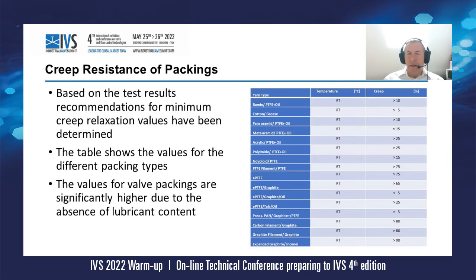The table shows the different packing types that have been tested. We start with ramie, PTFE and oil, cotton grease packings, para-aramid and meta-aramid, both with PTFE and oil impregnation, acrylic, PTFE and oil, polyamide, PTFE and oil, Novoloid, PTFE impregnated, PTFE filament packing with a PTFE impregnated dispersion, ePTFE, and the different types of ePTFEs, graphite with oil, and talc and oil, and then the carbon-based packings like Preox, PAN with graphite PTFE impregnation, carbon filament with graphite impregnation, graphite filament with graphite impregnation, and expanded graphite reinforced with Inconel.